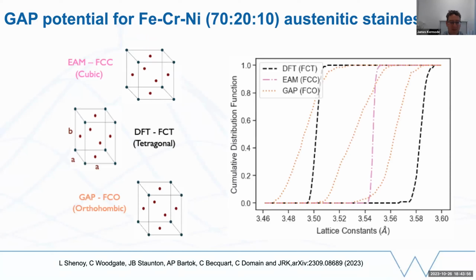The original GAP is sensitive to spin through the local structural deformation, but doesn't really know how to interpret it. It doesn't have information about the spin of particular atoms, and so can't really describe it properly. And so it gives you three different lattice constants, A, B, and C, all different, so an orthorhombic cell. But when we move to the spin GAP that includes spin information, we really manage to correctly describe the FCT structure, so the two short lattice constants and the one longer one really nicely.